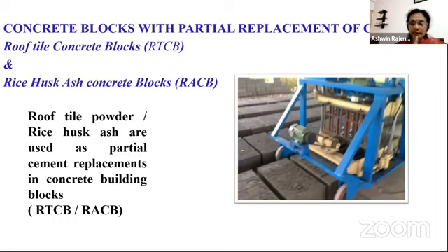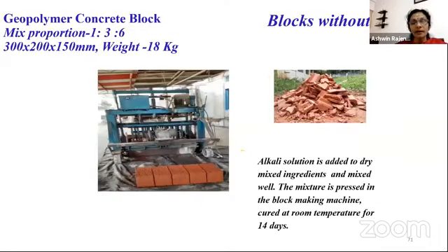So these are the sustainable technological options utilizing waste materials as alternatives to cement and aggregate, meaning partially replacing cement and partially replacing aggregate. Now the most important option, completely replacing cement. This is geopolymer. Geopolymer can completely replace cement. Alkali solution is added to dry mixed ingredients. Usually for the source material, silica and alumina should be there.